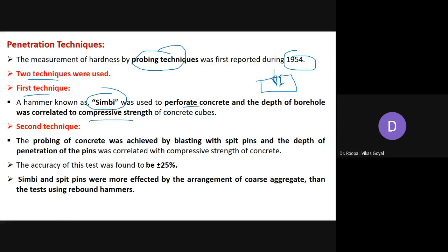In the second technique, probing of concrete was achieved by blasting with the spit pins. Speed pins dalte andar, and uska penetration depth measure karte hain. Okay, jitni bhi pins dali, uska kitna depth andar penetrate hua, and accordingly we are correlating with the compressive strength. And the accuracy of this test was found to be around plus or minus 25%.